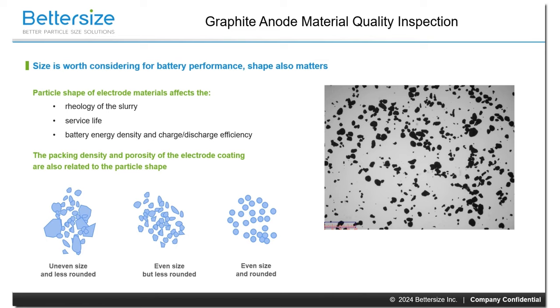As my colleague Dr. Barnum shared in her speech, both particle size and shape of anode particles are related to battery performance. The most ideal situation will be for all the particles to have a uniform size and rounded shape. But in the actual world, it would be hard to round the graphite particles to such a round shape, whether natural graphite samples or synthesized ones. So, people would take the situation in the middle. Thus, a relatively even size and relatively rounded shape would be fine. The picture shown on our right shows how a real graphite sample looks like. They do not have sharp edges, but those graphite particles are not in perfect spherical shape either.